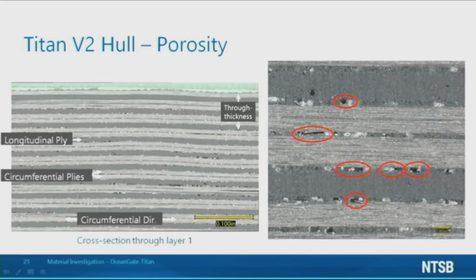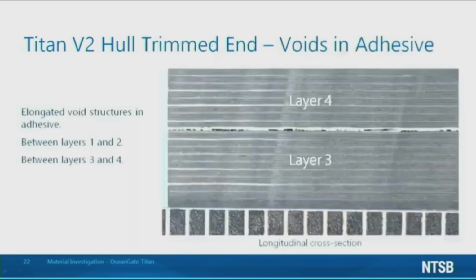In between the plies, there were thin layers of resin that contained porosity. A higher magnification image on the right of the slide illustrates this point. Several examples of pores within this fine resin layer are indicated by the red ovals. The amount of porosity within these resin layers was estimated to be between 18 and 27%.